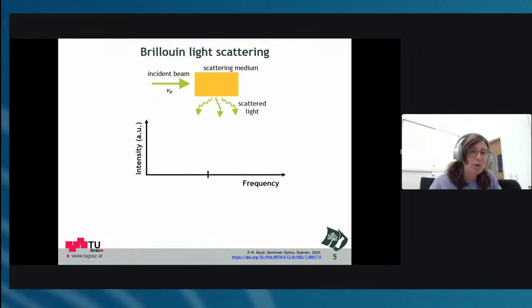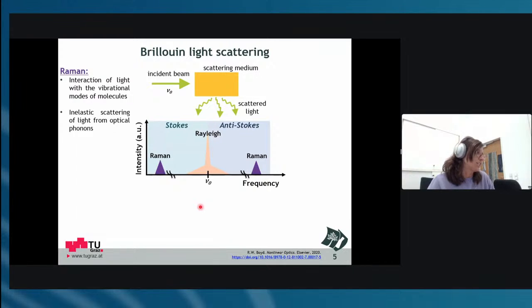So when you have a laser light and you shine it on a scattering medium, which is your sample, you will get scattered light. And there are different scattering mechanisms. There is Rayleigh, which is elastic scattering. It will stay at the same frequency as the incident laser light. And then there are two inelastic scattering mechanisms. One is very familiar, it's Raman scattering. Here the light interacts with the vibrational modes of molecules, or in other words, the light interacts with the optical phonons in the material.